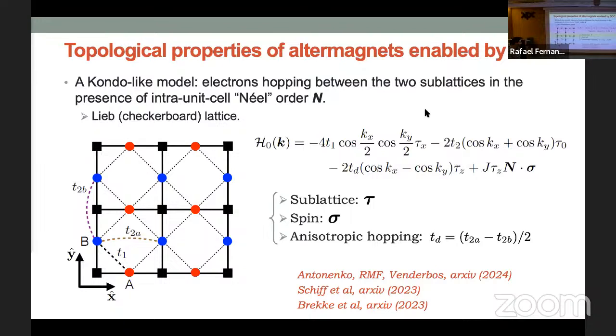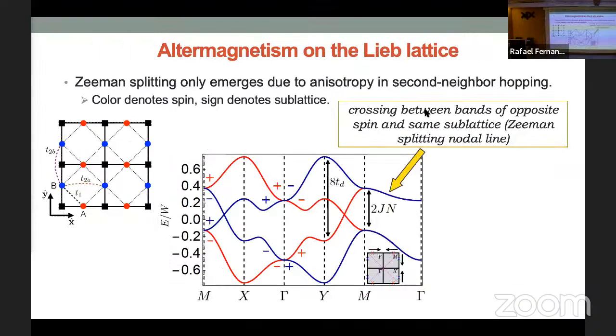Okay, and this gives rise to this term here. So we wrote this down in sublattice space and spin space. Now you can look at the band structure here, right? And here's what you find. I see splitting of order J between two copies of the bands, and these are the nodal lines. This is M gamma. So the nodal lines here are along the diagonals, and I see here red and blue are precisely the two spins. Great. So this is what I expected from an altermagnet.